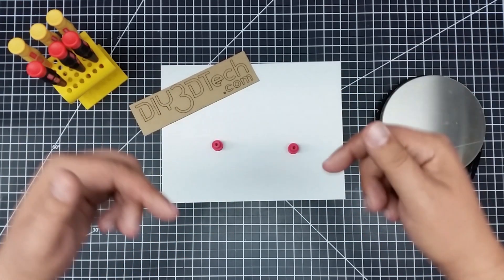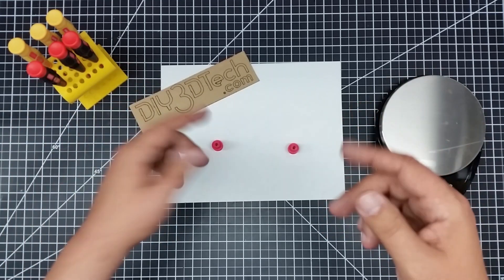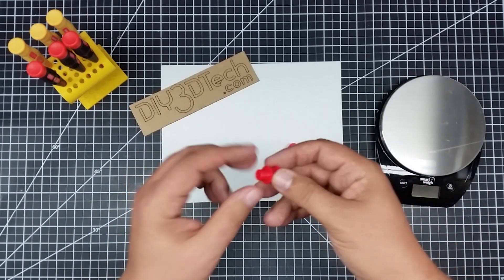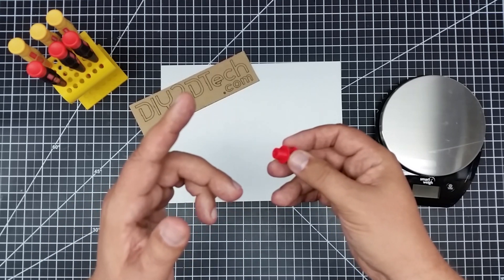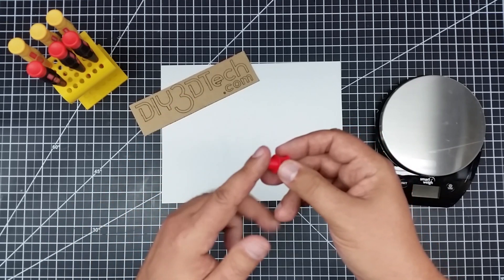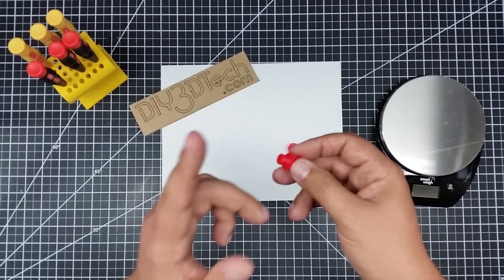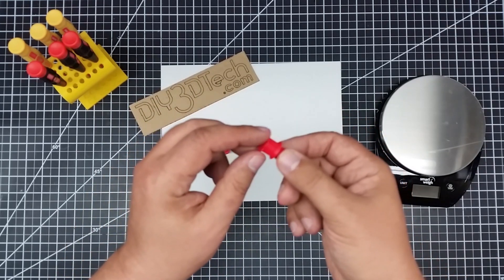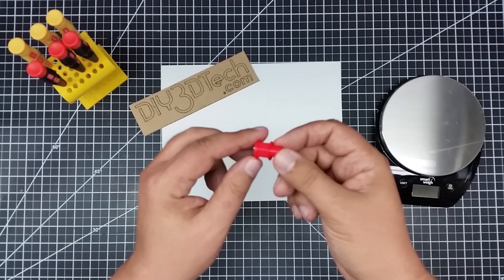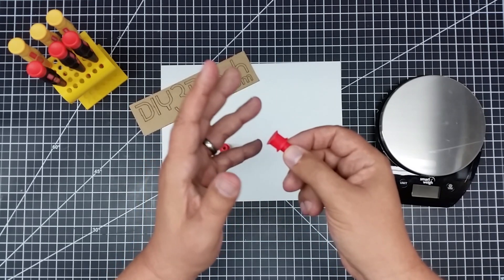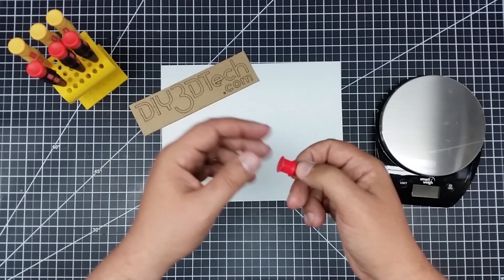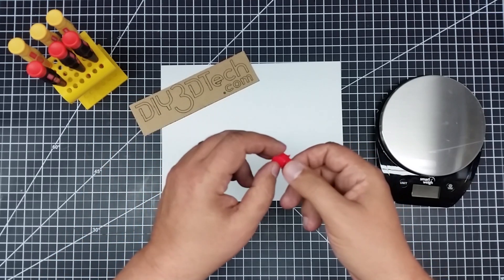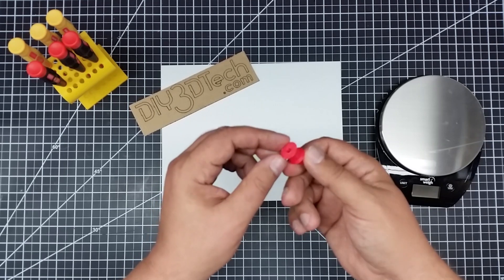If you know better, let me know in the comments below, but I got to say this really worked out nice. And I think the other piece with this, and the reason I wanted to try this, is I think this piece is far more robust. Because the one problem I have had in the past with these is after a bit of use, they want to start delaminating when I've used infill, even when I've gone up in infill, they've started to want to delaminate over time, especially with PLA.